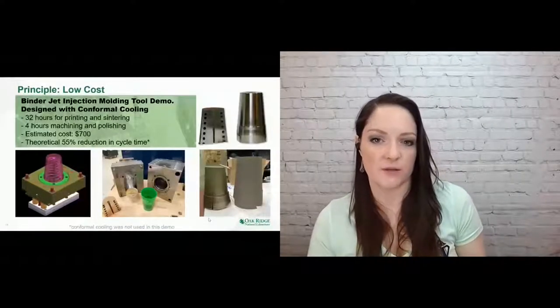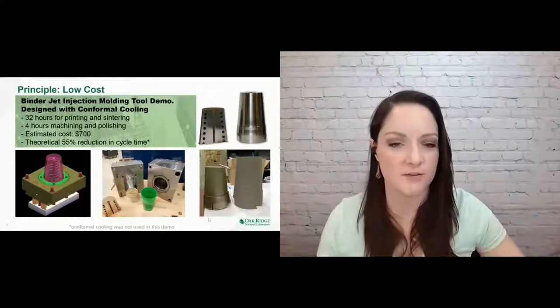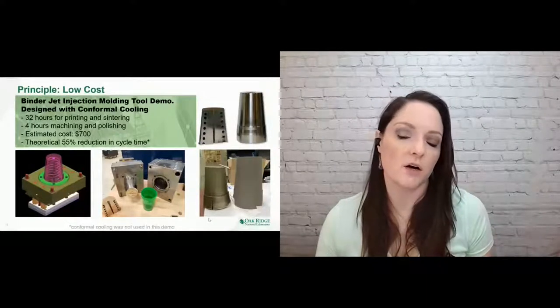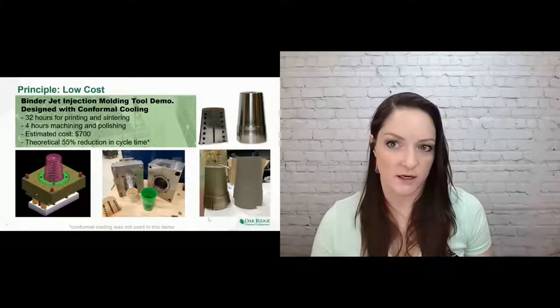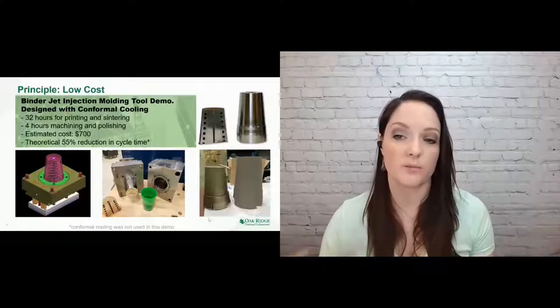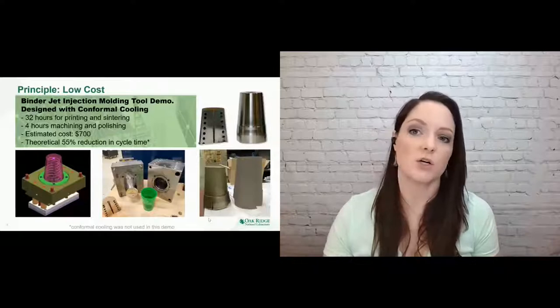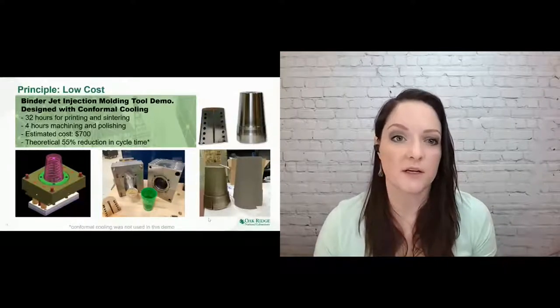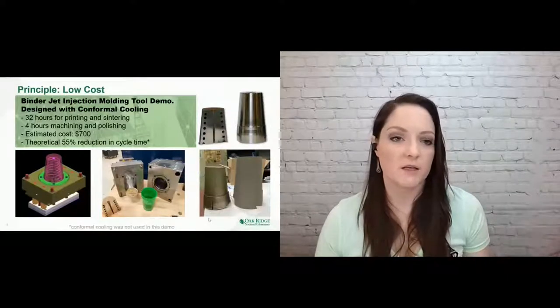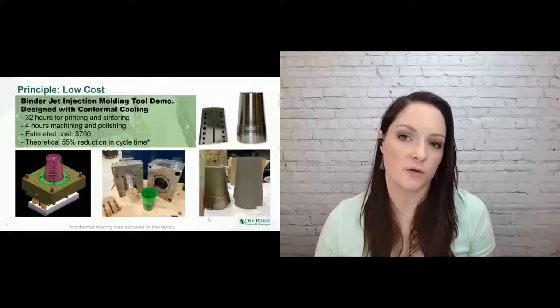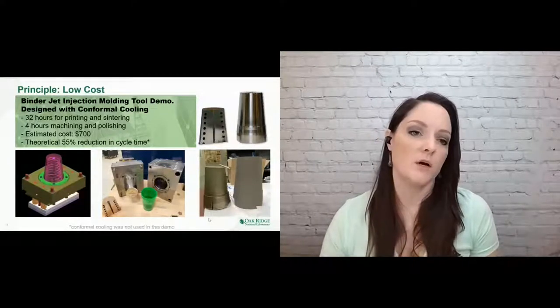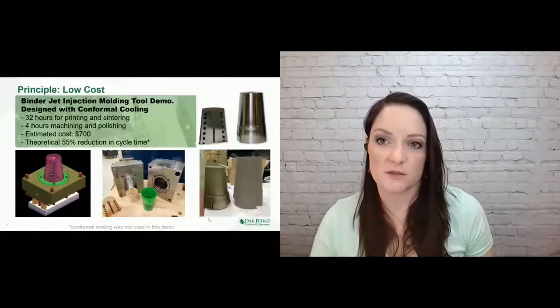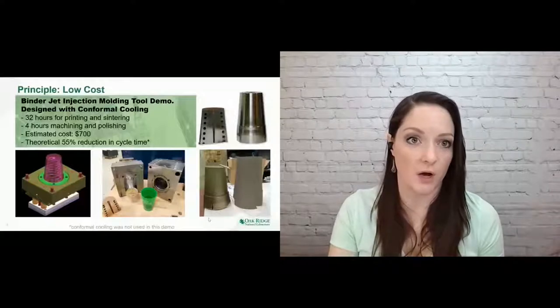Low cost. This is a demonstration that we did with binder jetting again. So my area of research is binder jetting. We are printing H13 tool steel, which is a very popular, common hot work tool steel, and sintering it to full density, which is kind of a new concept for binder jetting. Most people are used to the idea that you're infiltrating a steel with bronze, but that's not the limit. You can sinter these to full density if you know what you're doing. But what was the low cost part of this was we were able to make this tool at around $700, which is cheap for the tool itself, but we added this conformal cooling on the inside of the tool. And that in itself would have been another $700 at least if you were to do this with traditional manufacturing. But since we can add that into the model for free and the printer can print it for free, we can make these very high performance tools. Obviously, this performs a lot better because it has this conformal cooling. We can make these high performance tools for low cost.